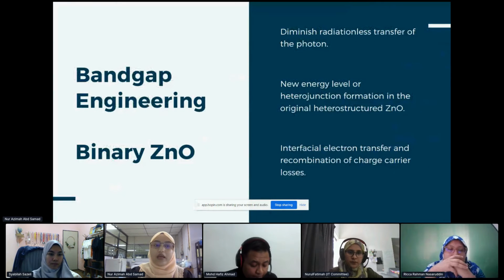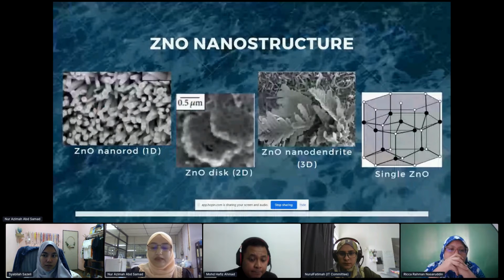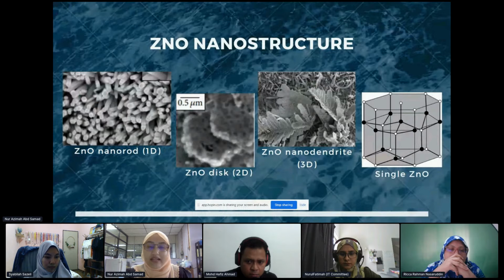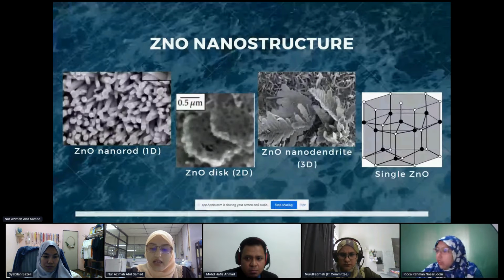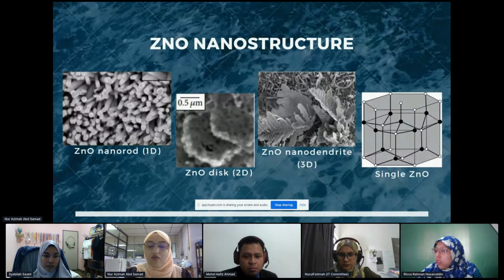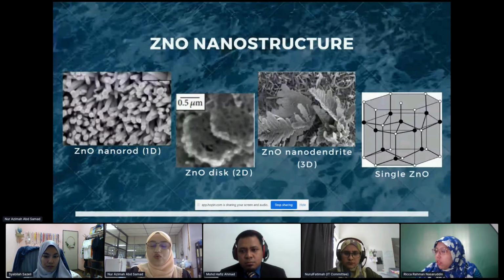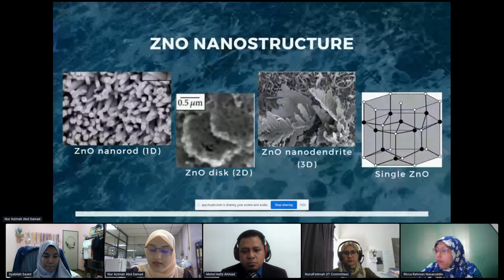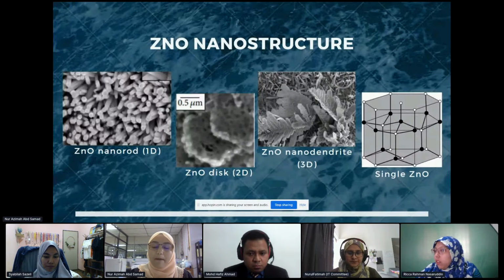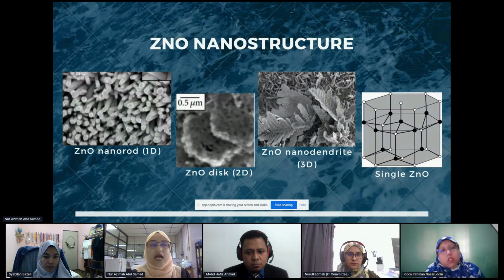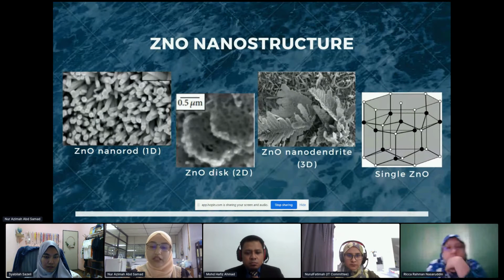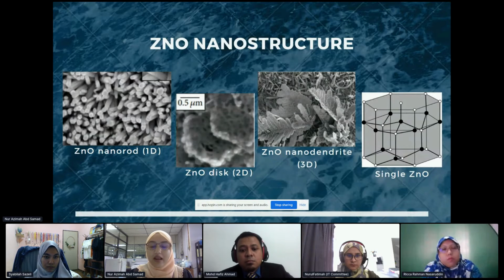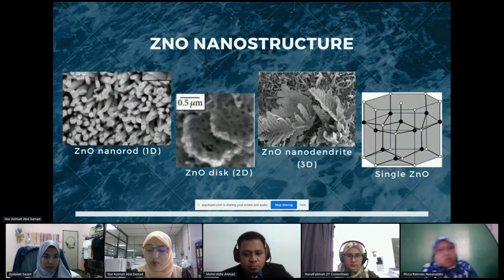However, as I said before, zinc oxide has quite a wide band gap, which is 3.37 electron volts, and I need to reduce it a bit to increase the charge carrier movement and also to reduce the charge recombination process. I also want to absorb the photon. Because 3.37 electron volts can only absorb photons with energy in the UV light. Yes, we need UV light to treat the bacteria. However, if we can benefit from the sunlight, it is even better.